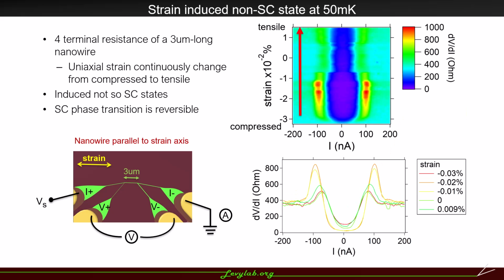Furthermore, we sweep the strain back and forth between tensile and compressed and observed hysteresis. This page shows result when we sweep the strain continuously from compressed to tensile, and again we observed strain-induced non-superconducting states.